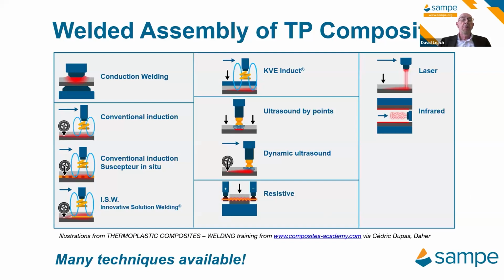A kind of proprietary system called innovative solution welding uses a moving susceptor that goes under the coil and heats, enabling the local area to be heated. But because that susceptor moves along, it moves out of the way, and so does not become incorporated into the finished joint. Koch and Van Engelen, owned by Daher in Europe, have their own proprietary induction system.